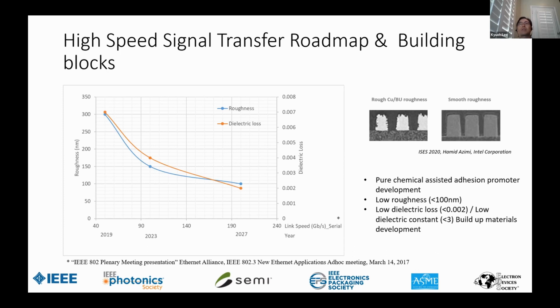Traditionally, in the current generation, in all the products in the market, there is about 500 nanometer roughness, which is very detrimental for high frequency signal transfer. So the roughness needs to be reduced to less than around 100 nanometers. That is for the traditional build-up material, with the wet process based electroless copper.